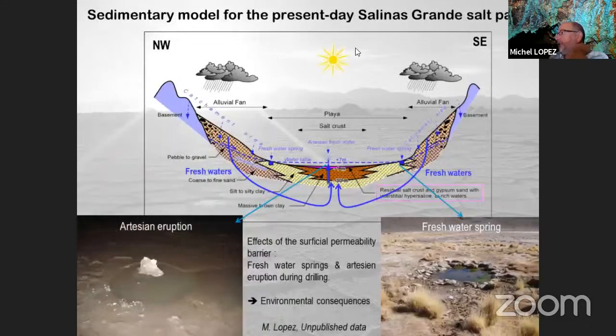Here is a sedimentary model for Salinas Grandes at more or less the present day situation. You have a relief with the basement, bordering the relief alluvial fan deposits, and these alluvial fan deposits are interfingered more or less with salt deposits and clay deposits. And the problem is during rainy season, the fresh water penetrates the alluvial fan deposits, goes down deep, and leads to an artesian water below. And in fact, on the border of the basin, there is some freshwater spring, as you can see here.